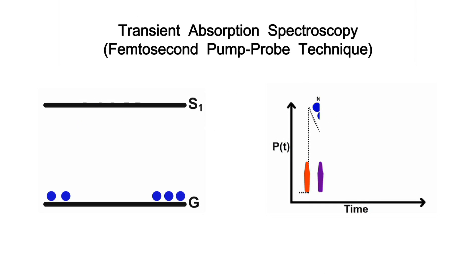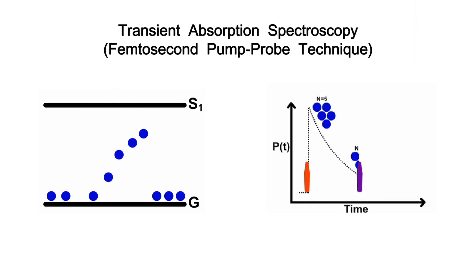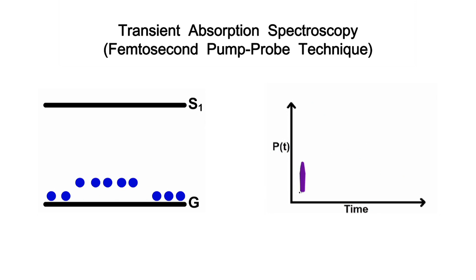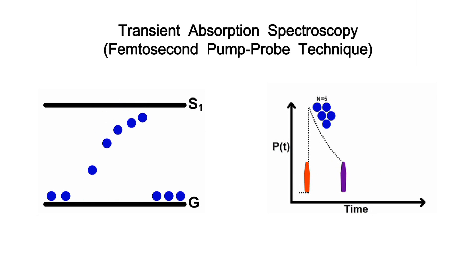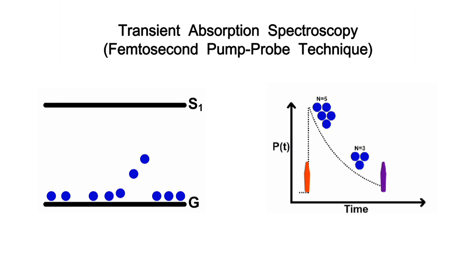Using a laser pump pulse to excite nanomaterials and a delayed probe pulse to monitor ground state recovery, we are able to understand how fast the charge carriers relax and how charge transfer occurs across the nanoparticle interface.